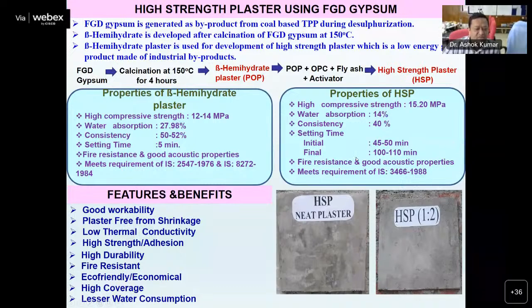The major features of this plaster are good workability, plaster free from shrinkage, low thermal conductivity, high strength, high durability, fire resistance, and so on. This high strength plaster can be used in neat form as well as a cement sand mortar by adding sand in 1:2 ratio.